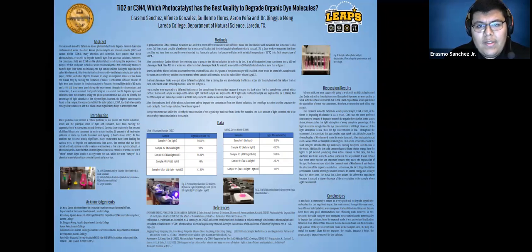Additionally, the solid semiconductor utilizes photon energy from the light to get excited, and this produces some active species. It was noticed that these active species are important because they cause a degradation of dye. Furthermore, the UV light had better performance than other light sources because its photon energy was stronger than the other ones.